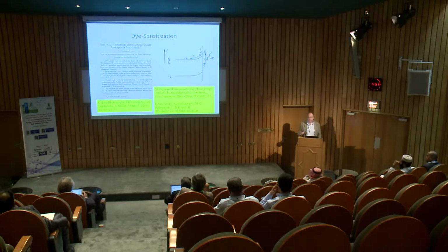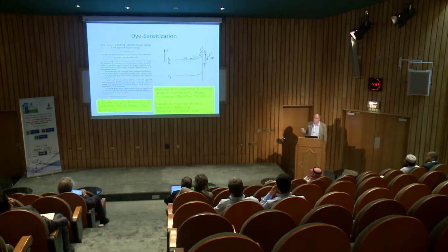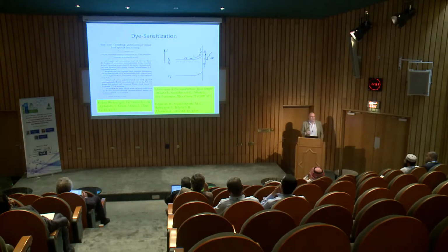with colors, let's say. So he used the silver halides and then put a natural dye, erythrosine dye, on the silver halide and could obtain with visible light, if you can read it here, about 1/4 of a volt, he mentions. So he could see an electrical effect on dye molecules on a semiconductor. And also very nice, this is actually the complete paper, so it's very concentrated, very efficient. So I think it's a nice example of that.